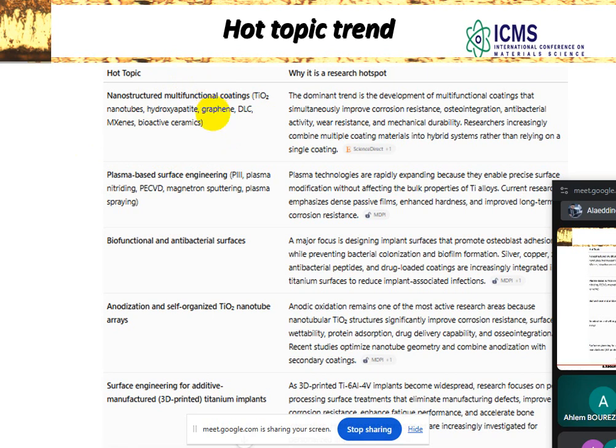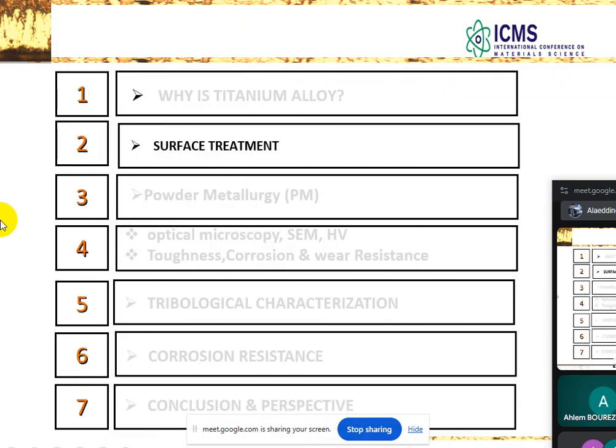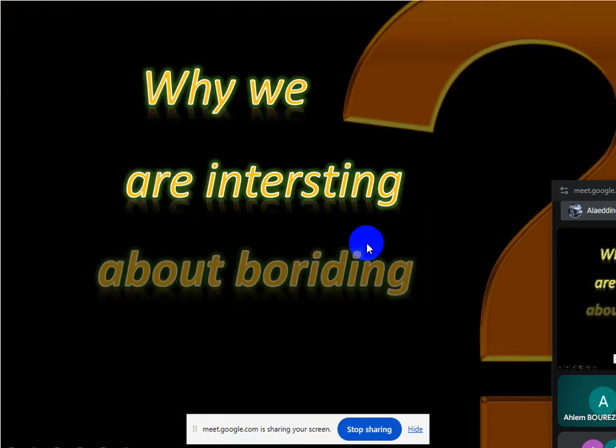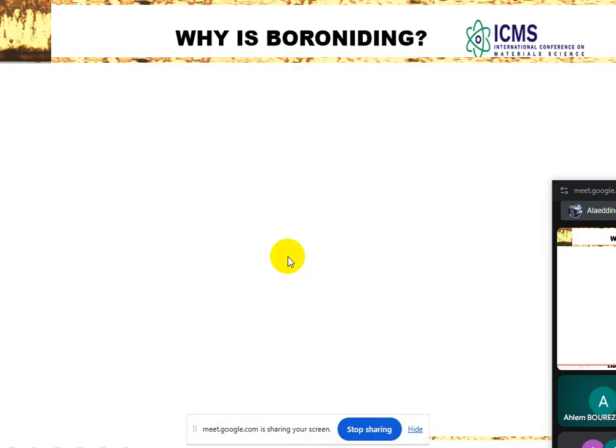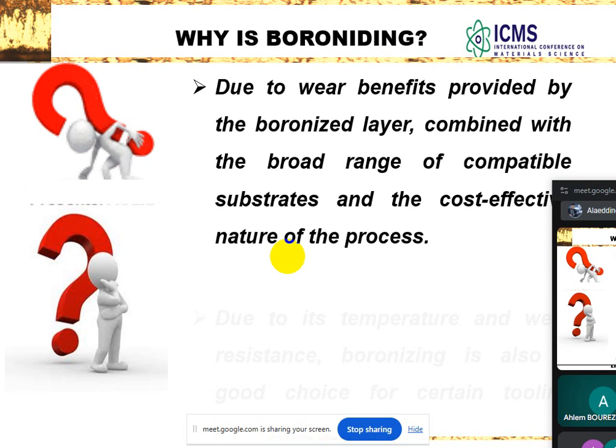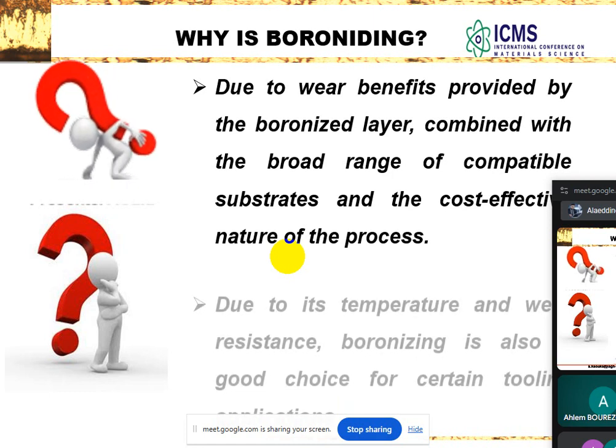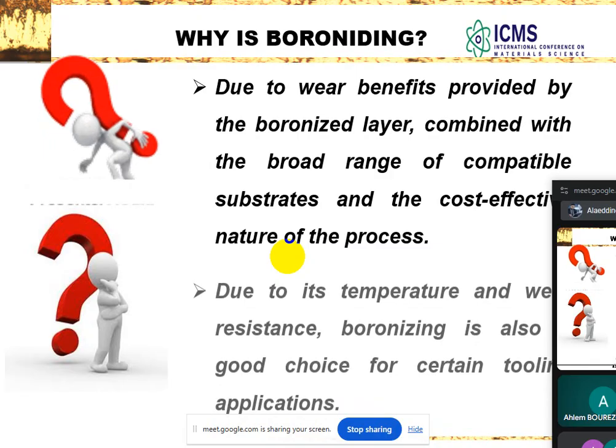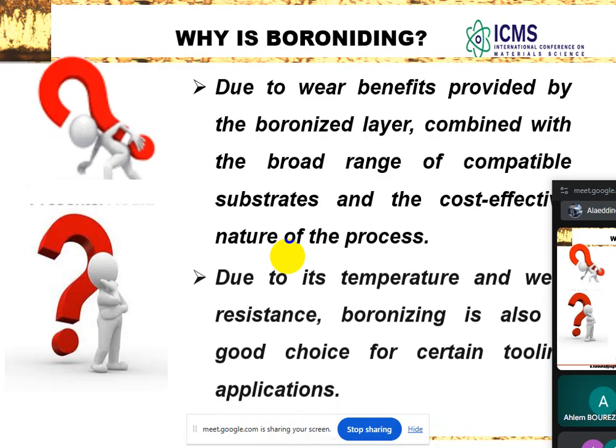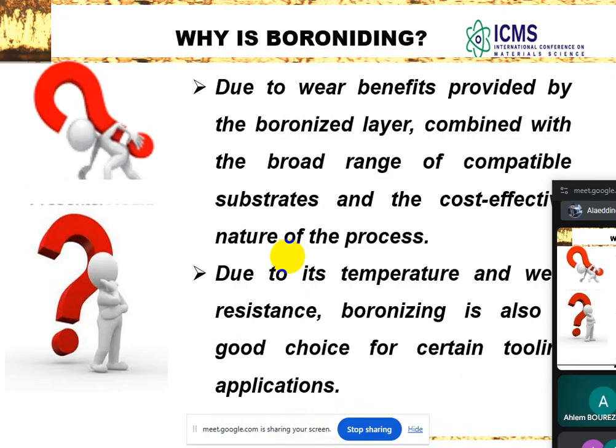So we are interested in improving the surface of titanium alloy. And you can see here, you can click only in Science Direct or MDPI to check other publications. So our work focuses on surface treatment with boriding. Why are we interested in boriding? Because boriding, as you know, is a very important thermochemical surface treatment, in which boron diffuses into the surface of the treated material. This material can be iron, cast iron, steel. We have many publications about this material. However, we focus on titanium alloy.